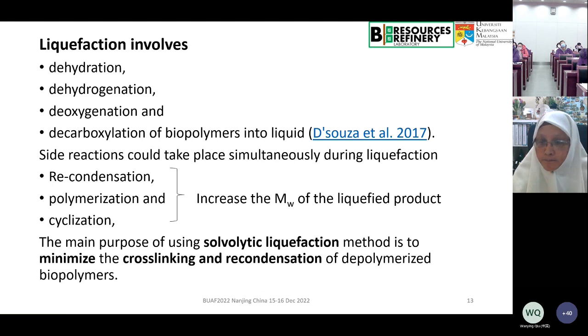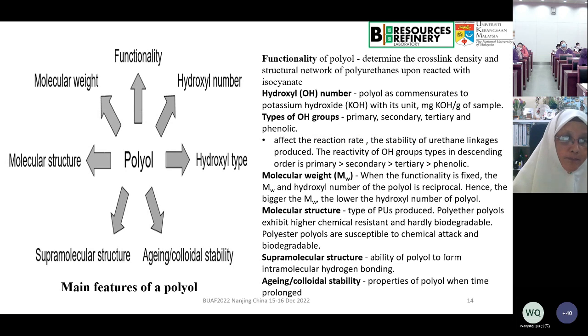So liquefaction involves dehydration, dehydrogenation, deoxygenation, recondensation, polymerization, and so on. Especially polymerization, when you handle lignin, it tends to polymerize because lignin forms radicals at high temperature. So that's why if you want to handle lignin, you have to use the lowest temperature possible. If not, then you have to have a certain technique so that it does not polymerize, so that you don't have so much residue at the end of the products. So now I'm talking about the polyol, because polyol is very important as far as functionality is concerned.